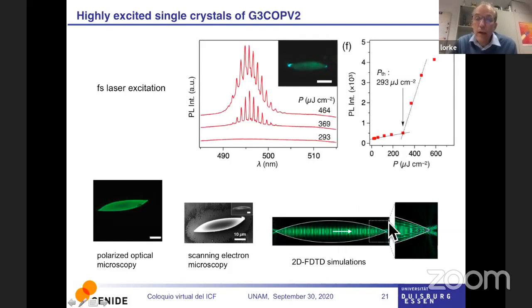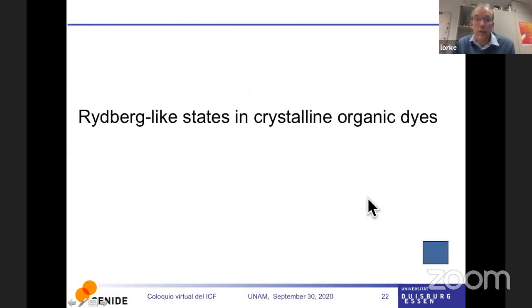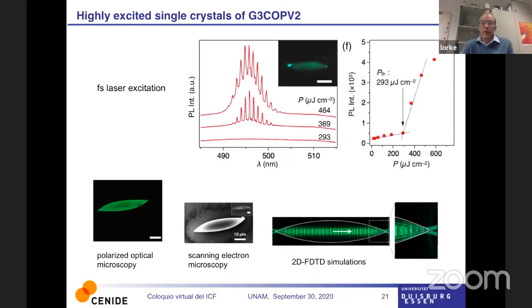Here you see some theoretical calculations, two-dimensional finite difference time domain simulations that were done in Jena. And you see that the light is mainly coming out of the tips here and the tips here. And that's exactly what we observe in the experiment. So this very nicely fits together. So we're there. We have shown something that looks very suspiciously like laser action.